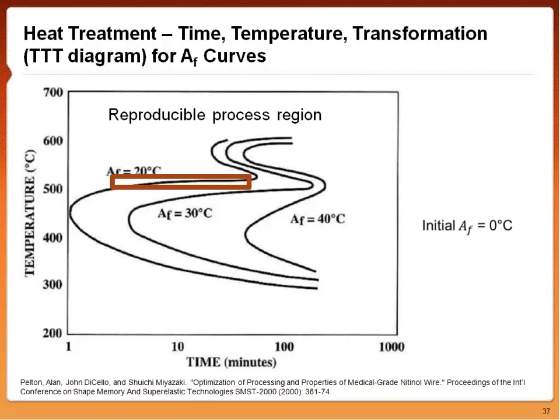So taking this point to operate on your TTT diagram to change your AF or shape set your material is not the best thing. You want to reach a region over here on a plateau where you're not going to see much of a difference between 8 minutes and 10 minutes in your processing time, and you're going to get that AF temperature that you want. This part of the curve is more stable to your processing, so it produces more repeatability in your processes and in your devices.